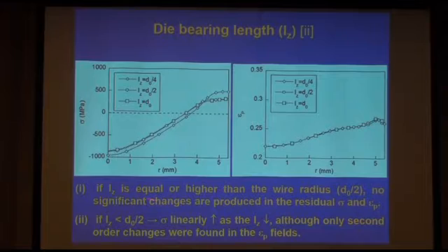If this bearing length is lower, this is not admissible, because in this case the hydrostatic stress linearly increases as the bearing length decreases, although only second order changes were found with regard to the strain fields.